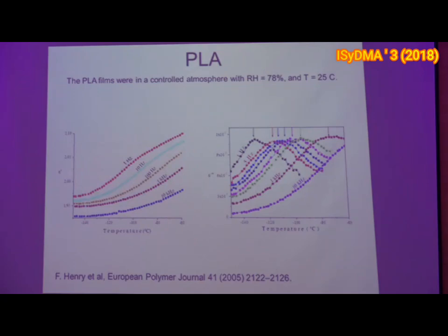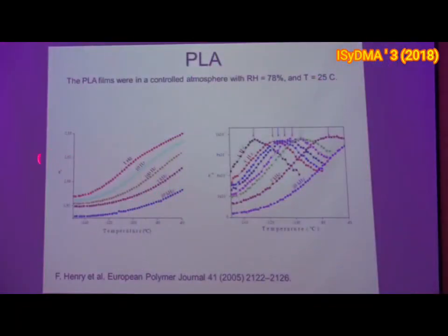So the results for PLA, polylactic acid. We kept the films in a container at relative humidity 78% and a constant temperature of 25 degrees. And then we can see the temperature dependence after a certain time, okay, for example, 3 days. We can see the variation with temperature of the epsilon prime, the real part of the permittivity.